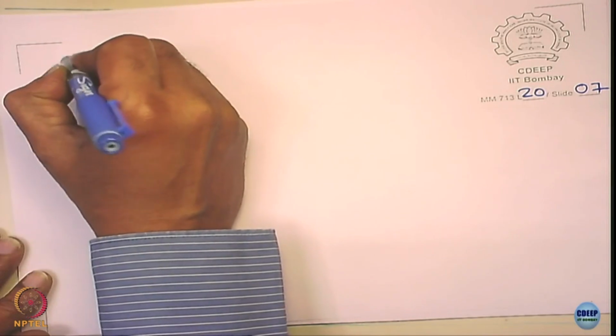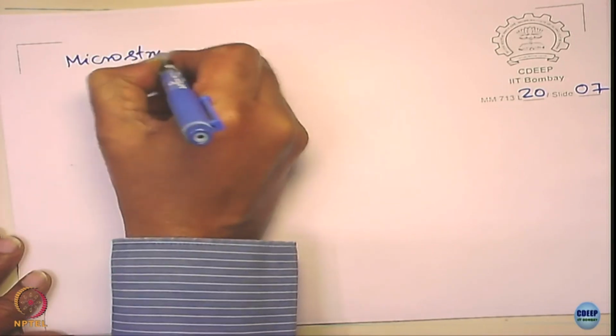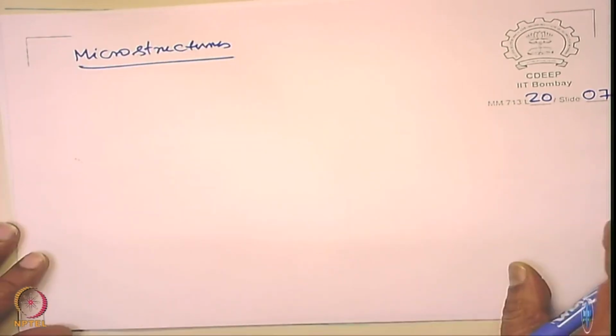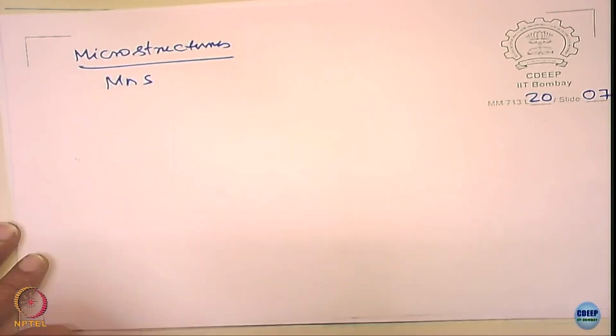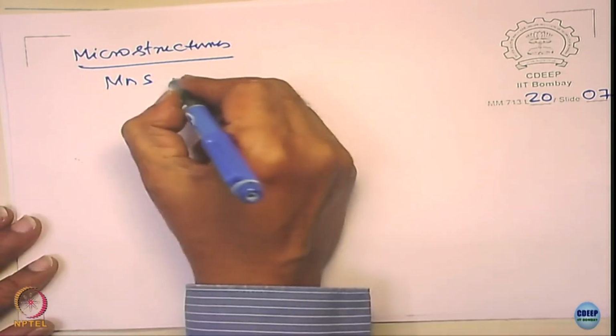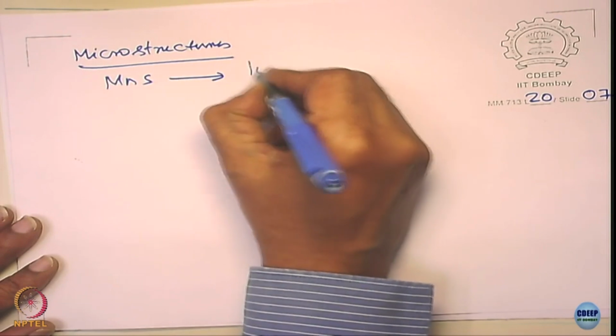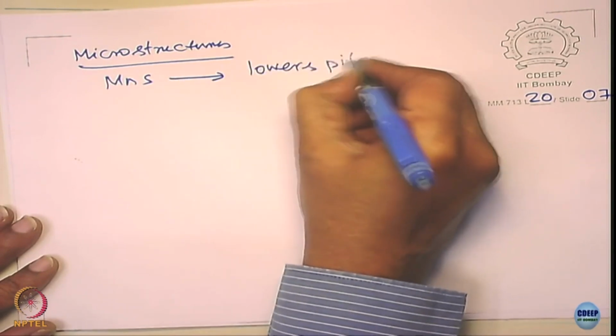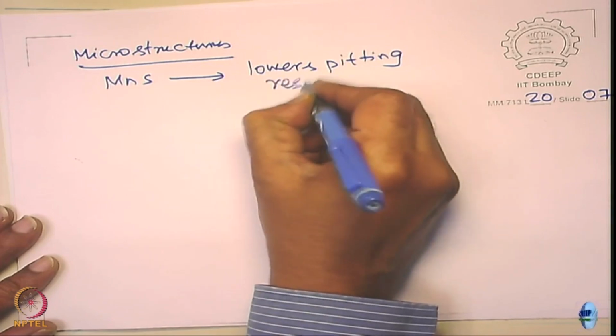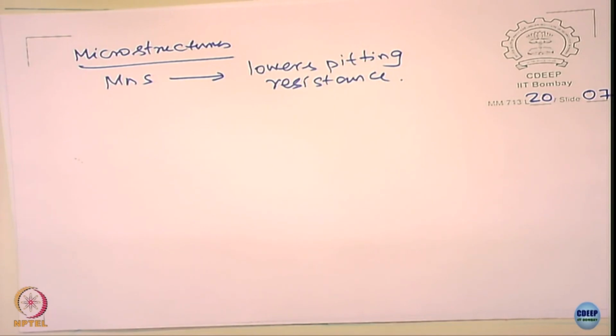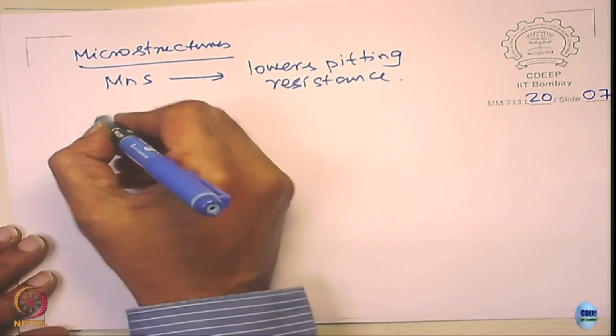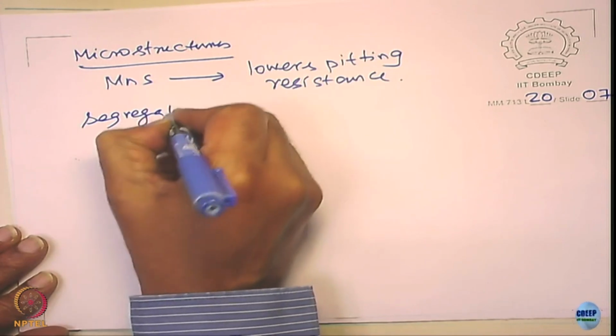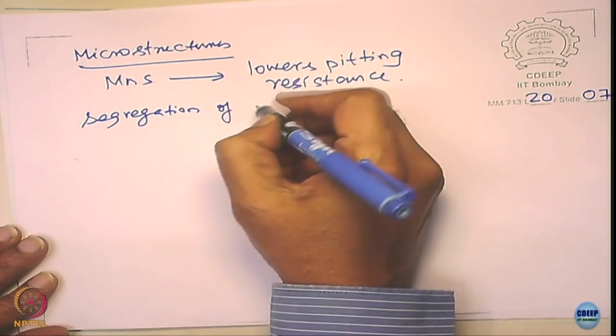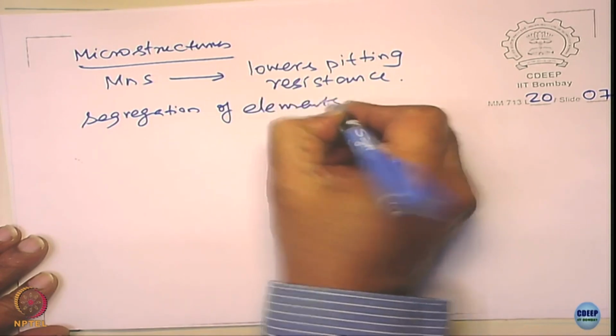Now we also have the microstructures. Let us go to microstructures. Suppose you have some phases which are selectively corroding, like manganese sulfide, what happens? It lowers pitting resistance. They selectively dissolve, attack actually. So any phase which is prone to corrosion will promote the corrosion. Similarly, segregation of elements promotes pitting.